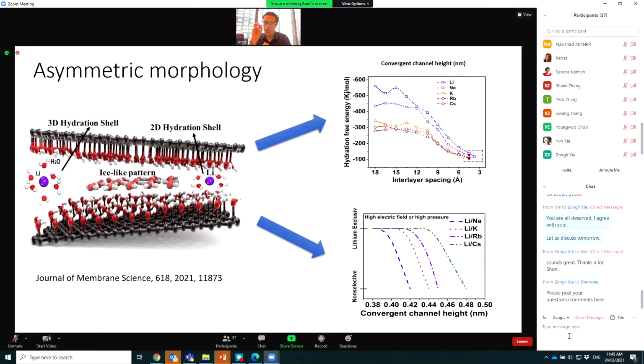because lithium, putting hydrogen aside, in alkali metal ions has the smallest diameter, and also it has the ability to play around with its energies, for example, Gibbs free energy, hydration energy, binding and trapping energy, and all of those energies that are important during this ion transport.